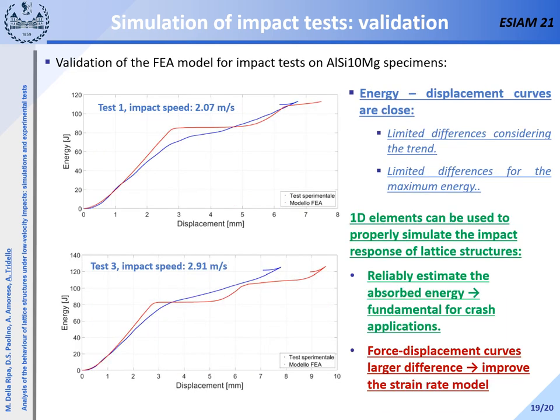On the other hand, the finite element energy-displacement curves are close to the experimental curves, with limited differences in the maximum energy regardless of the impact speed. Therefore, it can be concluded that the proposed model with 1D elements and its simple strain rate simulation can reliably be used to assess the stored energy, whereas it is less accurate for modeling the force-displacement curve.